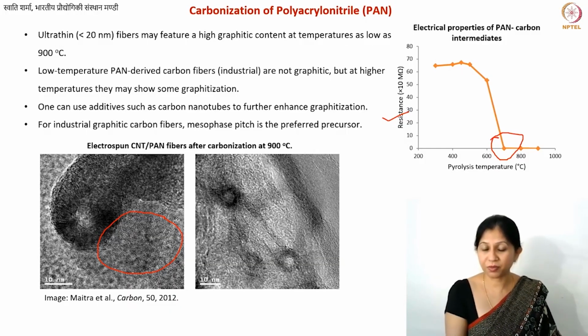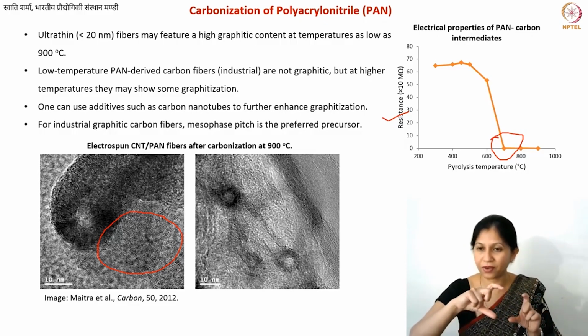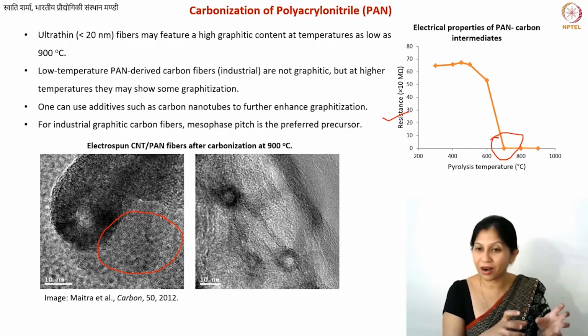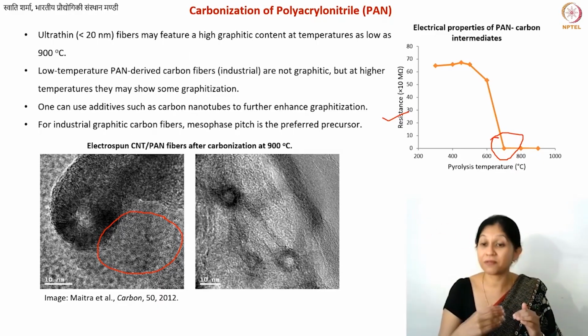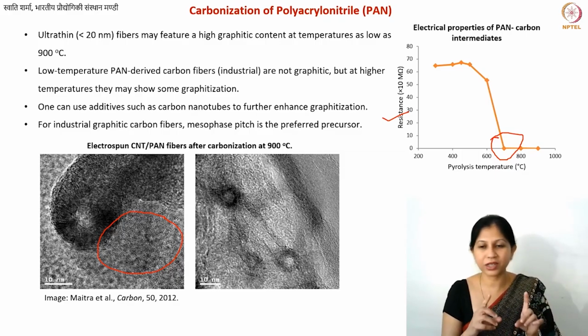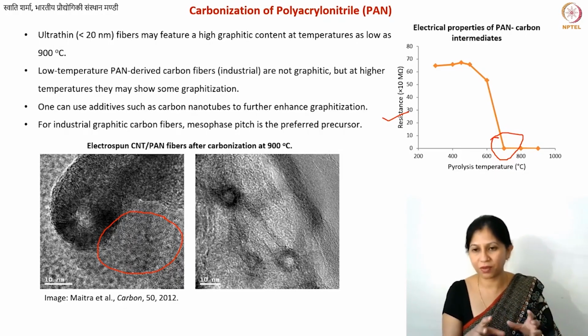However, as I have mentioned before, for industrial graphite fiber fabrication, there is a difference between graphitic and graphite. Graphitic is the content of graphitic crystallites, typically in a disordered carbon material. As long as you can detect the graphite peak in XRD or any other spectroscopic or diffraction analyses, you can call it graphitic. However, graphitic does not mean that there is any given fraction of crystallites. So it can keep on increasing, and that is why you will say that the graphitic content keeps on increasing at higher temperatures. This is valid for all carbon materials, not just fibers. But non-graphitizing would mean that it will never convert into perfect graphite. That is what we have in the case of PAN fibers.